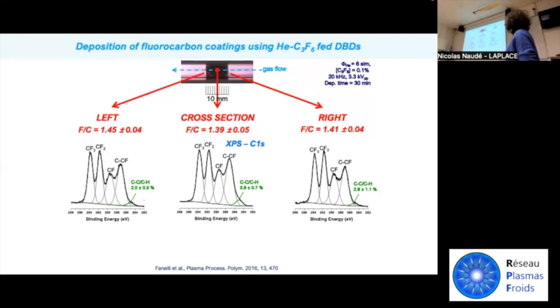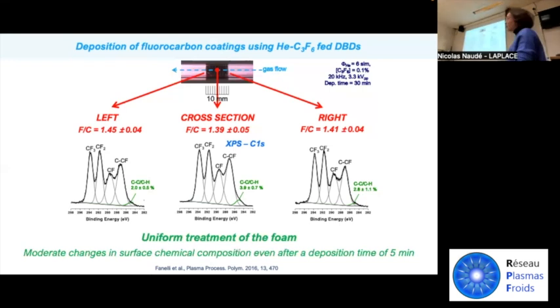The contribution from the hydrocarbon component, that can be ascribed both to adventitious carbon and to the coating and to the substrate, is always very low. And also the surface chemical composition is very uniform if we look at the surfaces directly exposed to the plasma, that is the left side, the right side, and also if we look at the cross-section of the foam. In addition, we observed only a moderate change in surface chemical composition after a deposition time of 5 minutes. This means that even if the deposition time is low, we could expect to have a conformal coating, a uniform coverage of the complex material.